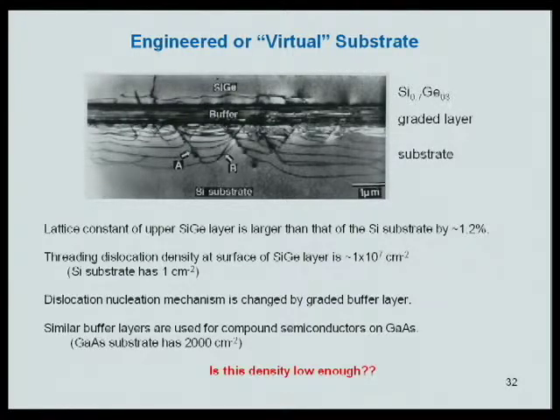But the question we ask ourselves: this still has some dislocations running up to the surface. Each of these dark lines, by the way, are dislocations. We're seeing the high strain field of the dislocation in the image. Anyway, the question is, are these good enough for the various applications?